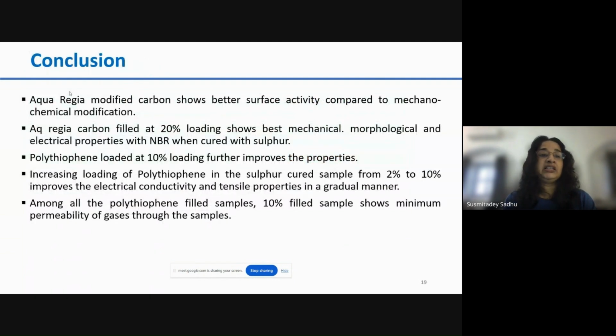So coming to the conclusion, aqua regia modified carbon shows better surface activity compared to the mechanochemical modification. Aqua regia carbon black filled at 20% loading shows the best mechanical, morphological, and electrical properties with NBR when cured with sulfur. Polythiophene loaded at 10% loading further improves the properties.